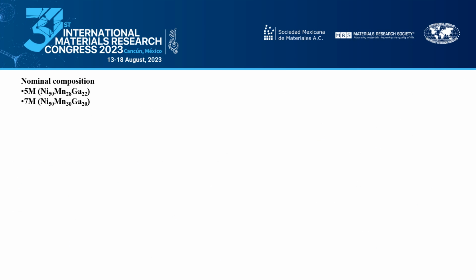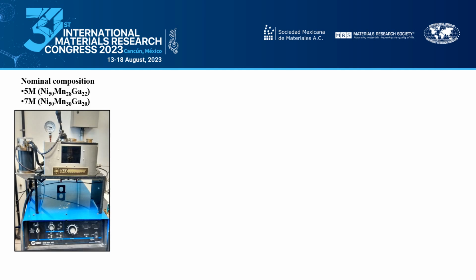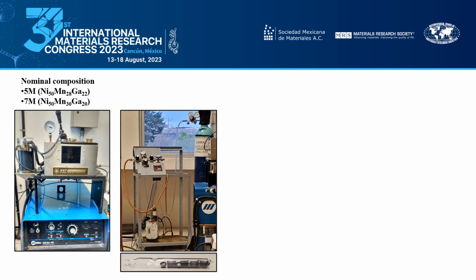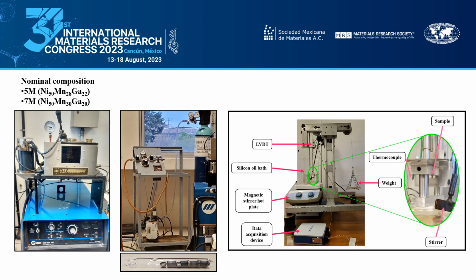For this work, the alloys' composition was adjusted to obtain 5M and 7M modulated martensite structures at room temperature. Polycrystalline nickel-manganese-gallium alloys were prepared by arc melting from high-purity metals, then were heat treated at 1073 Kelvin for 24 hours. Samples were analyzed by differential scanning calorimetry and X-ray diffraction. The length curves as a function of the temperature were obtained in a laboratory-built compression equipment, and then from these curves the elastocaloric effect was calculated.